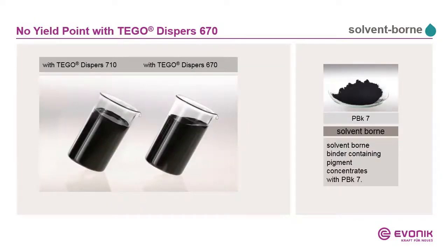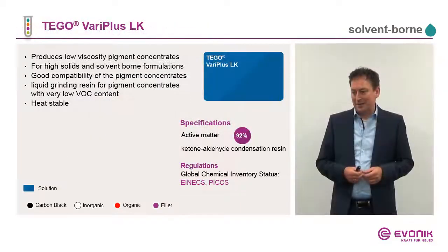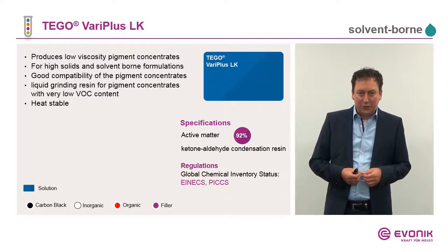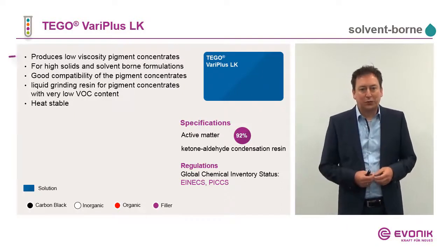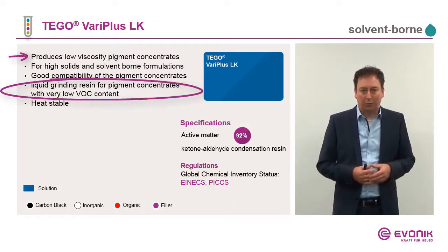The interesting thing is, beside the very good viscosity reduction, also that the 670 has almost no yield point. So it gives Newtonian flow behavior. And this Newtonian flow behavior that you can see here in comparison to the 710 is very important for instance for digital inks. It's not the topic that we are talking about at the moment, but you can also keep that in mind. Newtonian flow behavior from 670 wherever it is needed. TEGO VariPlus LK, our new grinding resin, gives very good viscosity reduction, was developed for low VOC colorants.